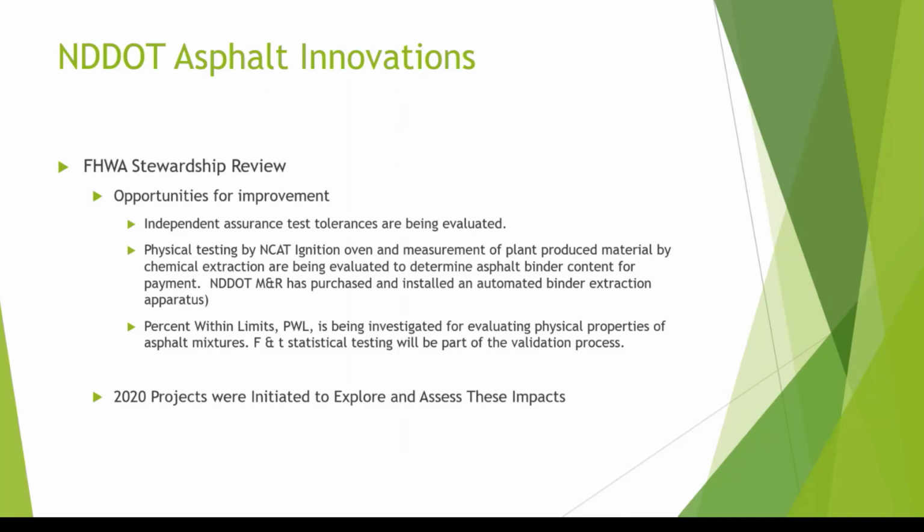It's very important in the field and at the paver to know that your asphalt content is staying consistent. And how do you get that? Well, we do takeoffs, right? Every night we do a check on the totalizer every time we pull an aggregate sample for QC or QCQA. But the accurate way of getting it, particularly when you have RAP in there, you're only measuring virgin asphalt. And what you have for asphalt content or effective asphalt content in the RAP is an important part of the process, because the mix only sees total asphalt content.